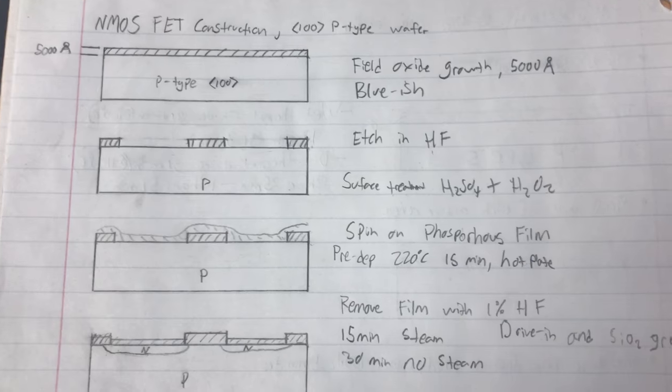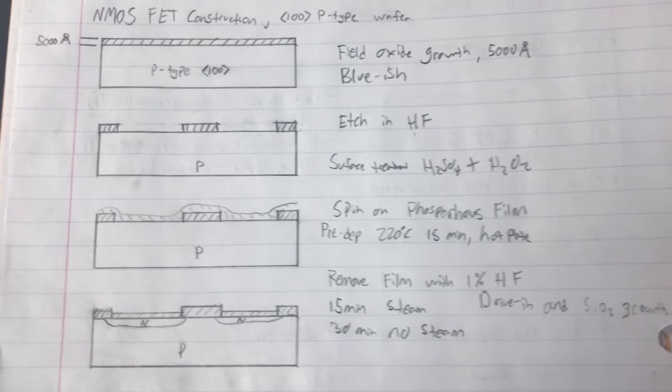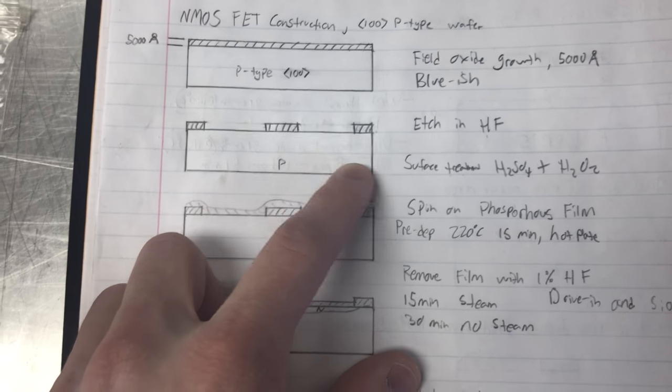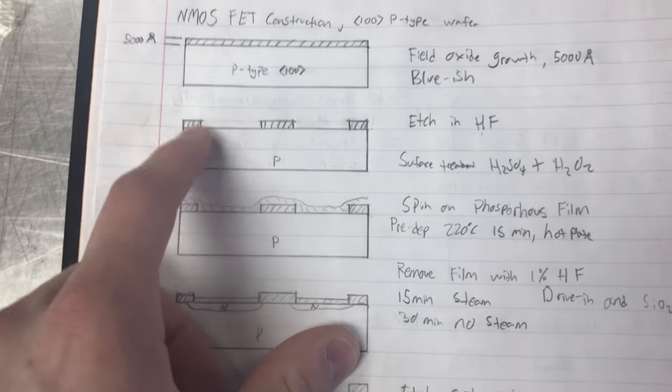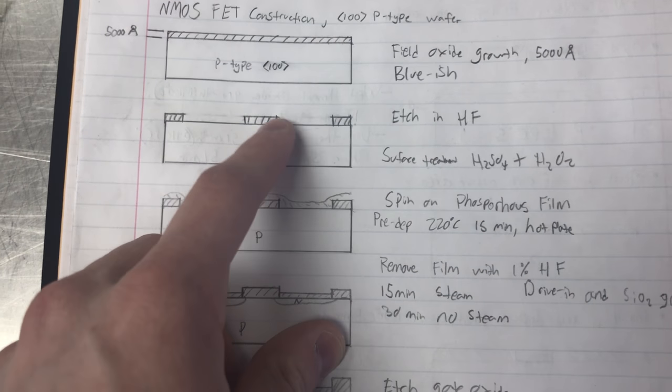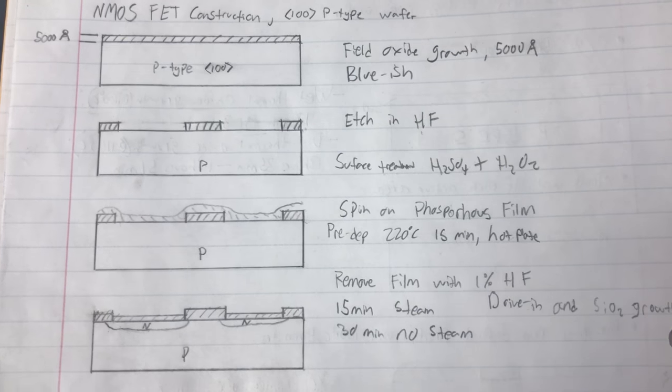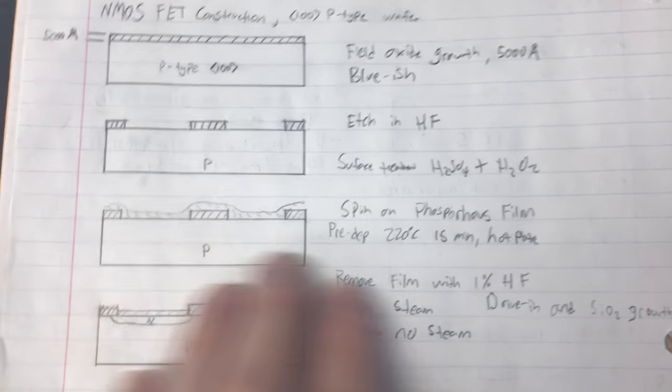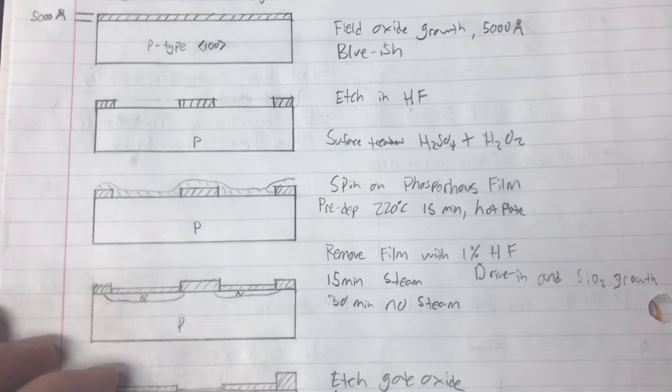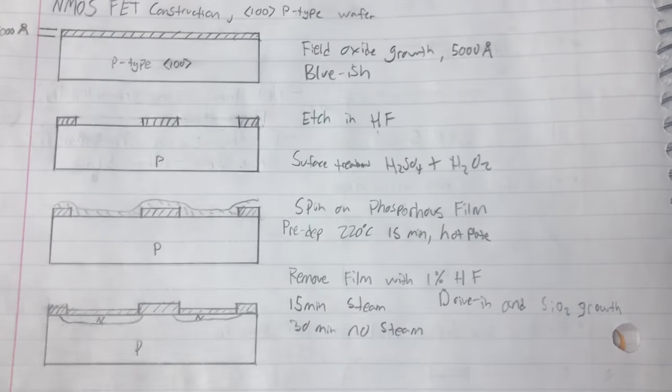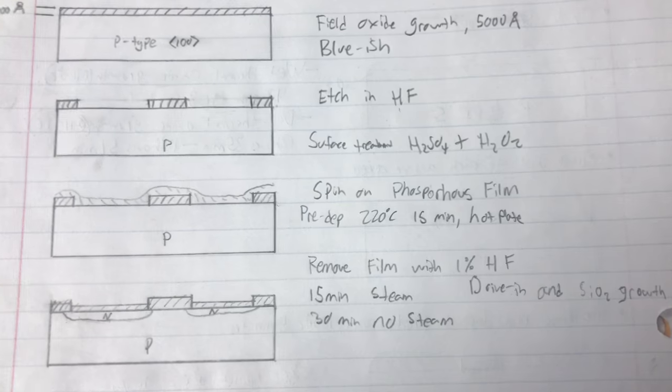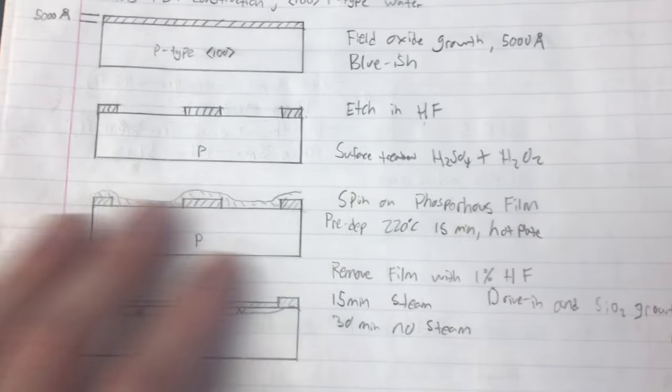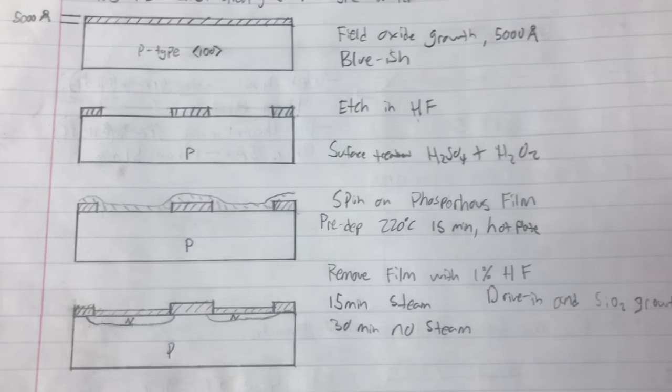So, you have to know roughly how much time it's been in the furnace for, and you can use an online calculator to figure out which region of the repeating color you're in, and therefore, you can get that color. I'll show you that chart in a minute here. And then, you can use either electrical tape or vinyl mask, or you can spin photoresist and expose it, but you're going to have to mask off portions, and then immerse this entire wafer in a hydrofluoric acid solution, so you can etch away these windows into the wafer.